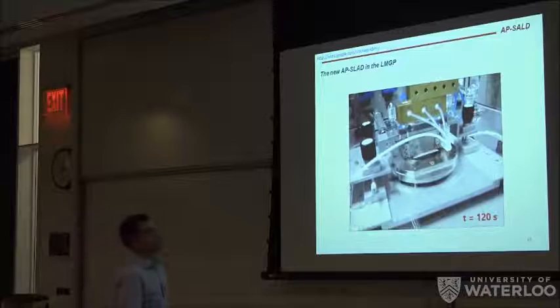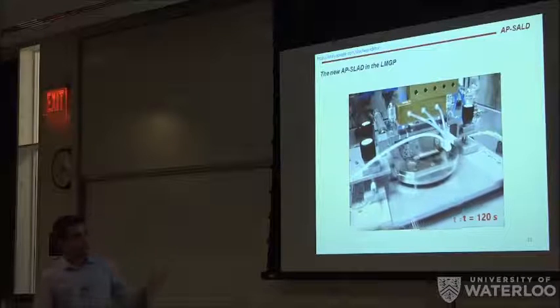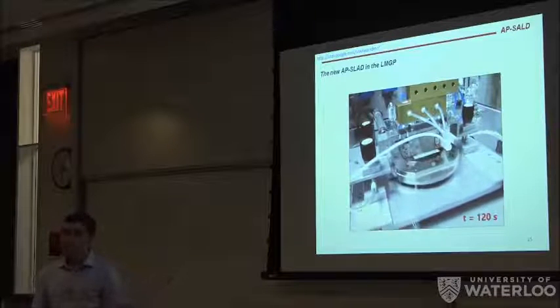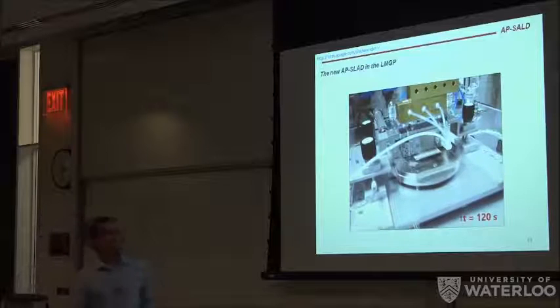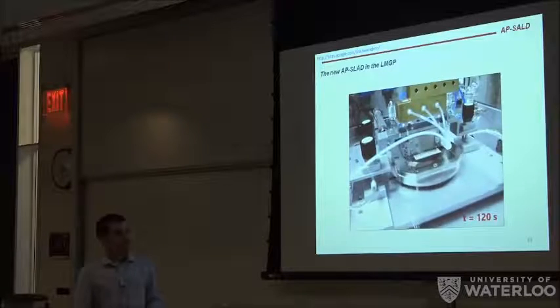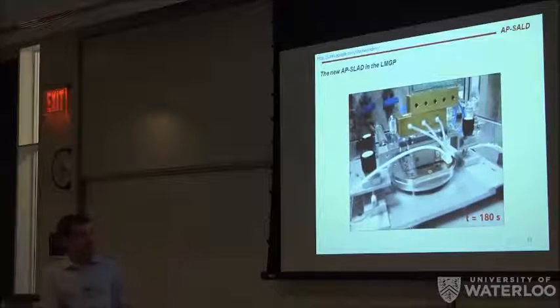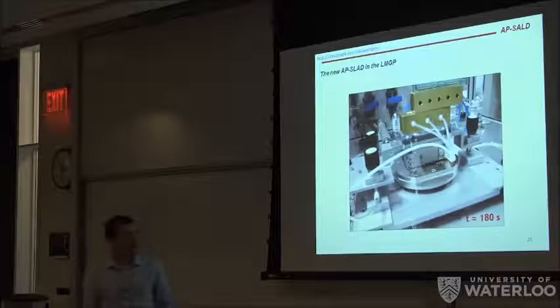We are at 2 minutes. You see it's much thicker now. And you will see that after 3 minutes, it's very thick. You can see the difference in color. It's homogeneous. It's around 100 nanometers. You can see how nice and bluish it comes.